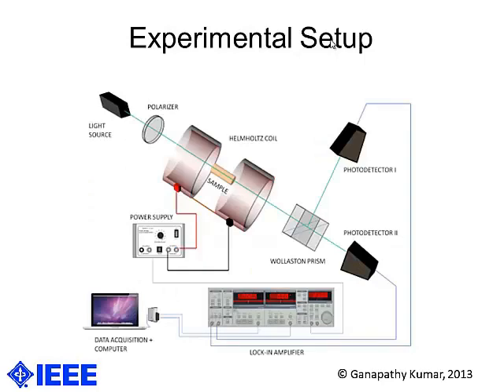For the optical measurement, the Verdet constant itself, we used a Faraday effect-based optical setup. So we have a light source, a polarizer, and a Wollaston prism for the polarizing components. And the sample is placed in the middle of a Helmholtz coil, which is going to be generating a parallel magnetic field. And then we have all the lock-in mechanisms and the data acquisition system.